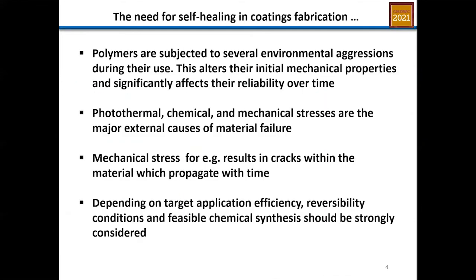So the need for self-healing in coating fabrications is simply because polymers are subjected to several environmental changes, and this will alter their initial mechanical properties as well as affect their reliability over time. And so several reactions involved could be photothermal, could be chemical, and they cause external material failure. And this mechanical stress, which produces cracks, will propagate with time. But the idea is, how can this be controlled? How can this be looked into?